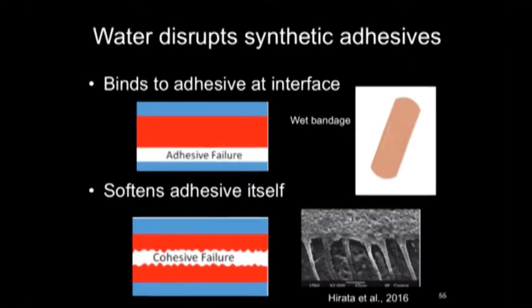But from the most simplistic perspective, water is typically disruptive to adhesives. Think about a wet bandage that you may have encountered at some point in your life. Sweat, or rain, or water from some other source causes the bandage to become less sticky. This would be an adhesive failure, where the water molecules are actually binding to the adhesive molecules of the bandage or tape or adhesive itself. So this image simply shows the two substrates. This might be the cloth or plastic of the bandage. The gluey adhesive would be this red, and then the substrate it's adhering to is this blue. And as the water binds to the adhesive, the adhesive is no longer able to bind to the substrate, causing failure and delamination or detachment.